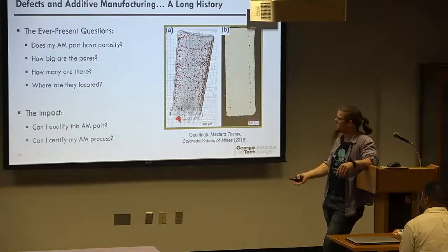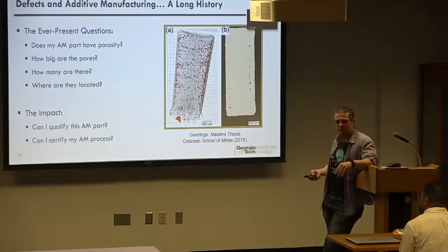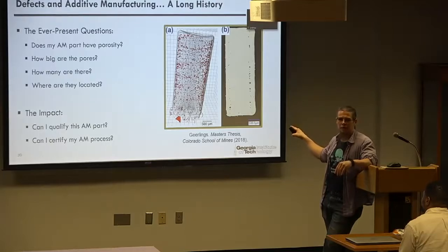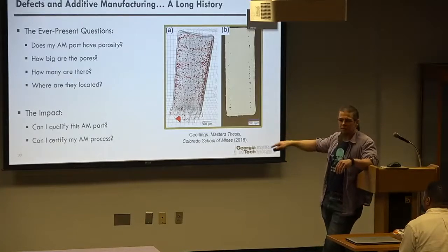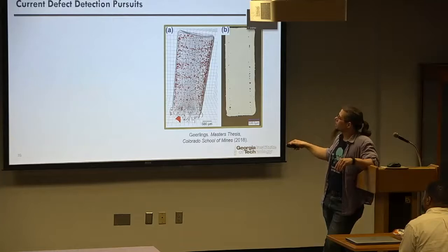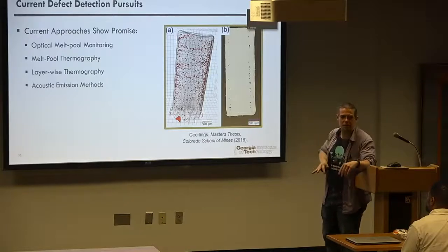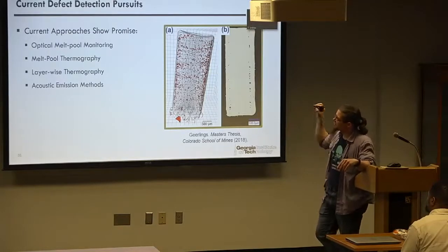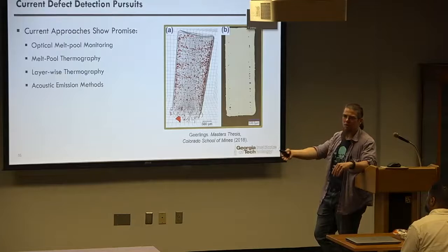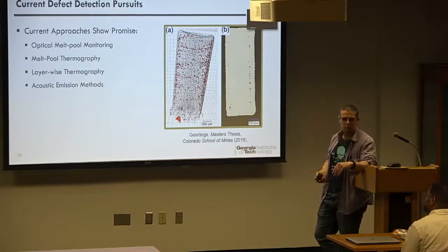The impact, the reason everybody's interested: can I qualify this AM part? And can I certify my specific AM process? If I don't know how big the pores are, where they are, if they're in a critical location, how many there are, then I can't actually say what the fatigue life is of this specific part, or what the fracture toughness is for this specific part, right? So that's why we're interested in defects. We haven't solved the problem yet. Current defect detection pursuits, right? Current approaches all show some kind of promise, but aren't there yet. We have optical melt pool monitoring, melt pool thermography measurements, layer-wise thermography measurements, acoustic emission methods. All of these are trying to quantify when a pore is formed and where it's formed and how big it is.